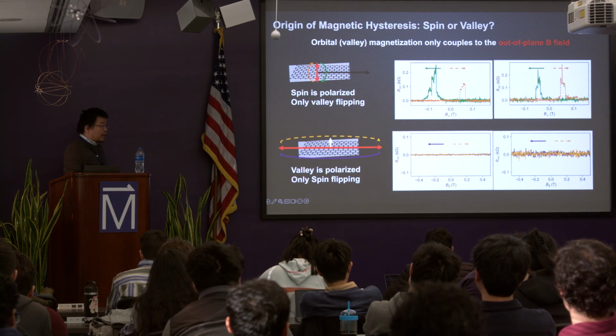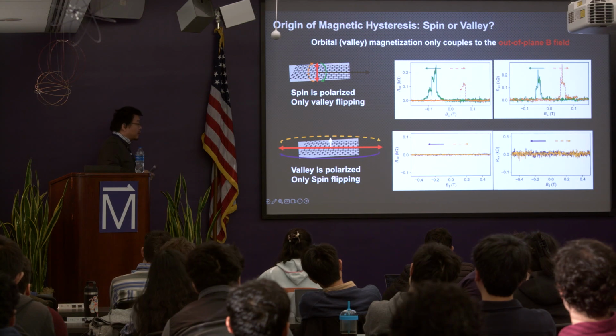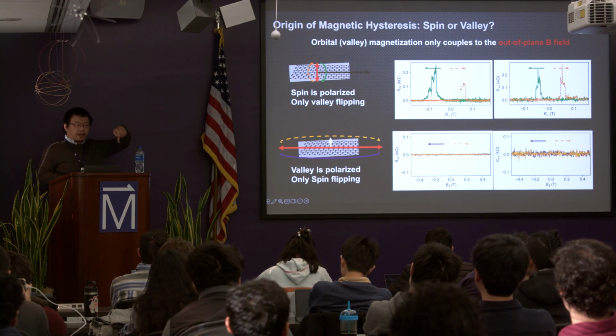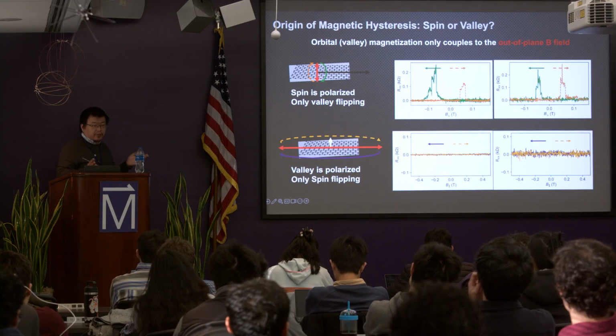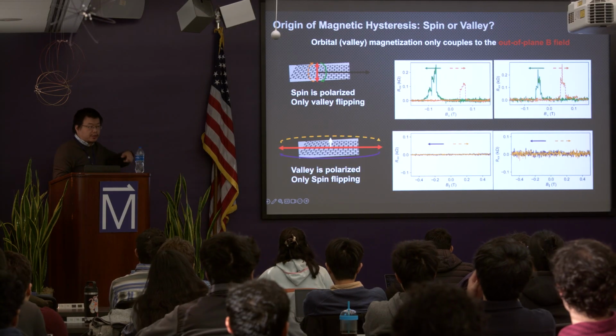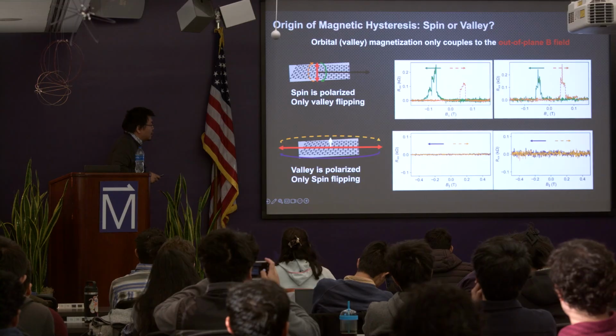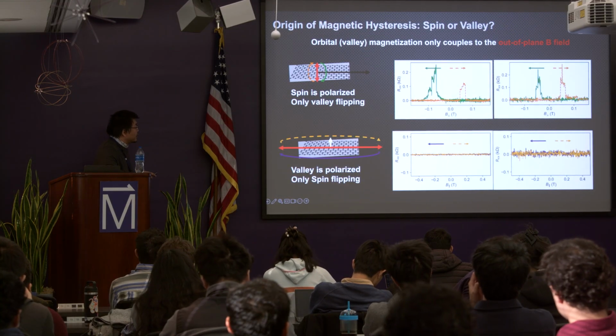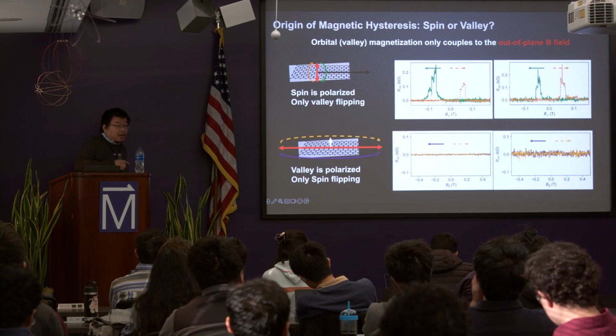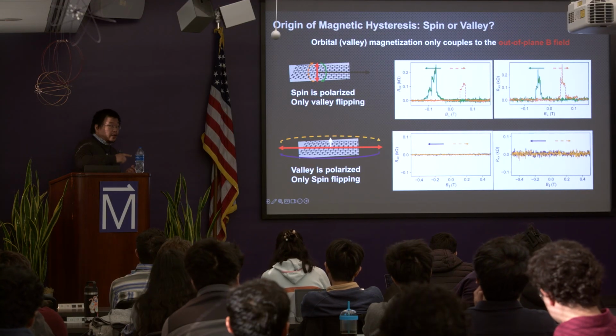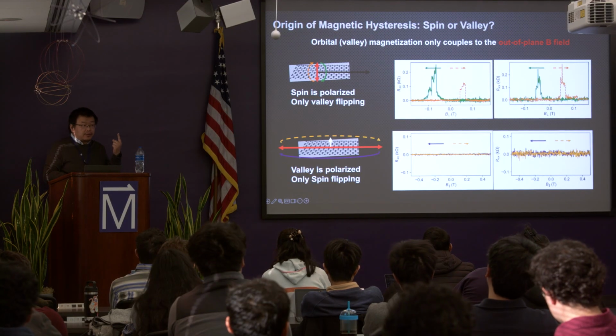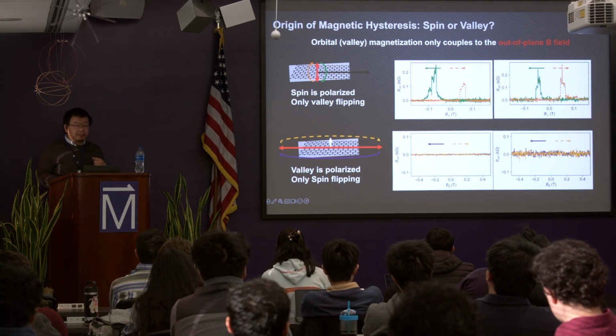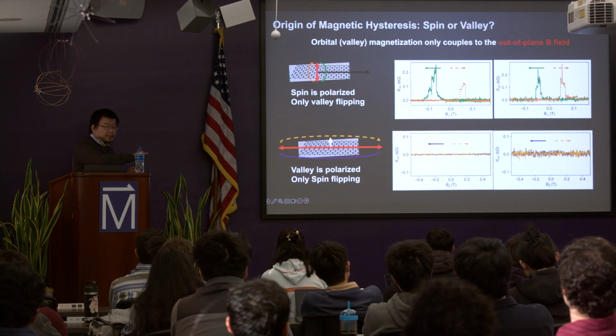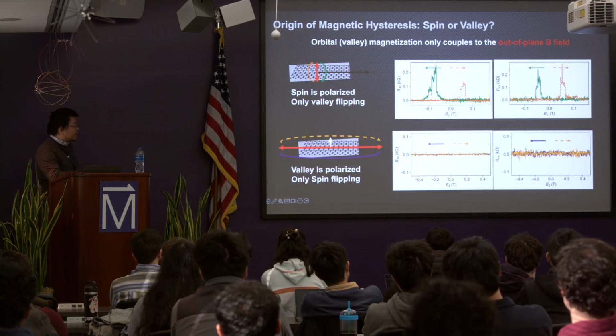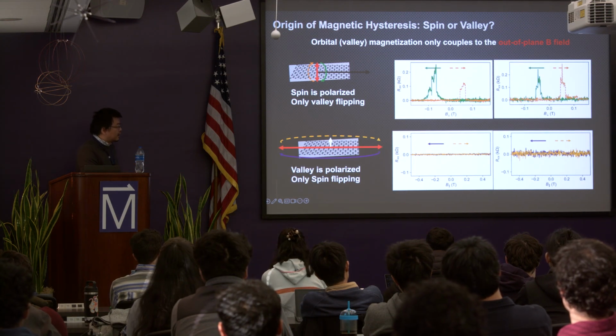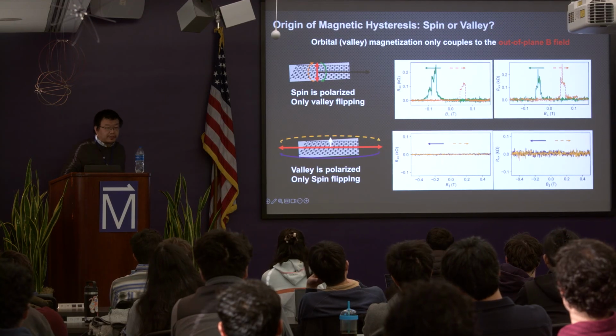So for example, I can do this type of test. For the orbital, it can only be either up or down. And for the spin, because of the very weak spin-orbit coupling, it can basically be pointed in any direction. So if I use the in-plane magnetic field now, to polarize the spin first, and then I sweep the out-of-plane magnetic field, if I still see hysteresis, that means it's from the orbital, because my spin is already polarized. Which is the case actually.